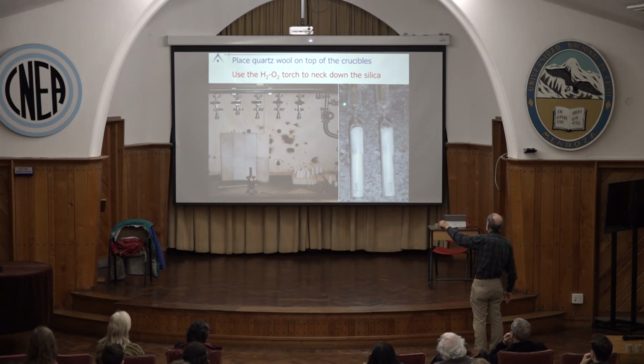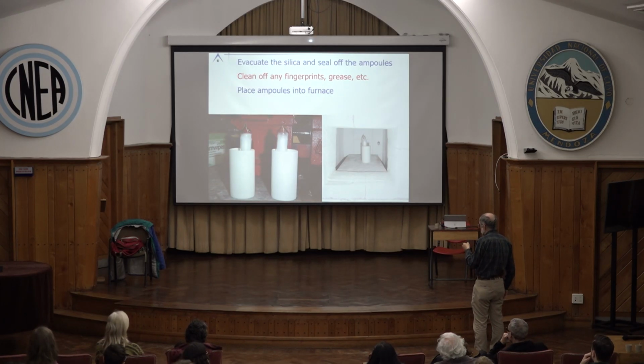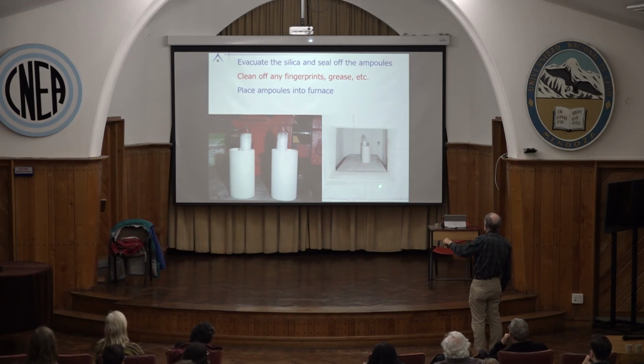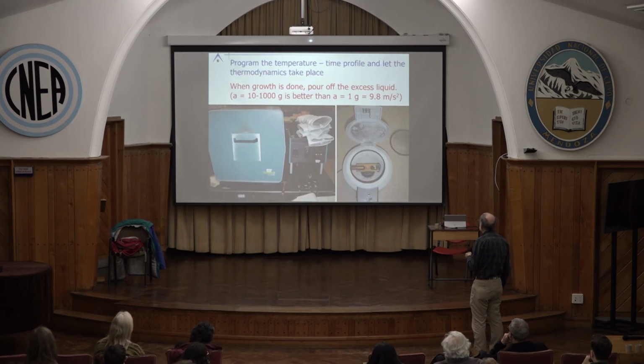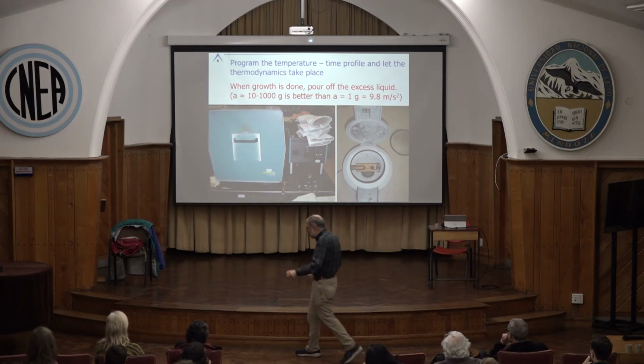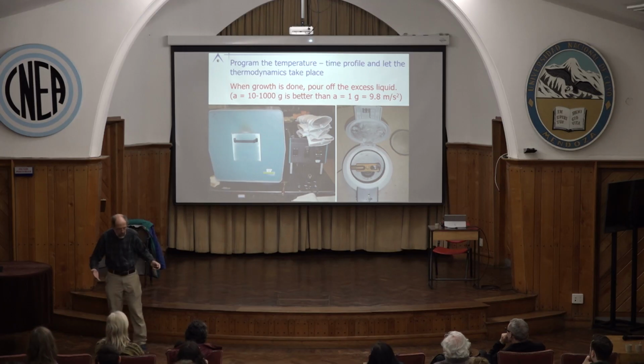I take the blowtorch, I make a nice hourglass-like thing. This is still connected, so I can pump. I hook it up to a pumping manifold. I do mechanical vacuum, backfill with argon, rinse it a few times, and then seal it off with the blowtorch. So, I now have each growth. The crucibles are down here. This is the silica wool cushion on top. There's the seal. I can put them into my furnace, and the furnace, for those of you caring, has a thermocouple, a hearth plate. I have heating elements above and below, and I close the door, and I heat it up. I dwell, I slowly cool down, I hopefully have grown my crystals, and now I'm sort of left with a dilemma.